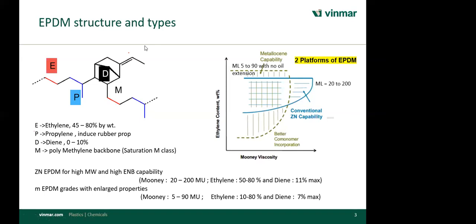Mostly in the world, EPDM is manufactured using solution polymerization technology. Only Versalis is making EPDM through slurry technology, and Arlanxeo has one plant for the slurry technology. Arlanxeo also uses their own innovation technology. The rest of the plants in the world are using either Ziegler-Natta or metallocene. Ziegler-Natta is the old technology, where the productivity of EPDM is low. Metallocene is the very first technology where you can get conversion up to 100% out of the reaction. In Ziegler-Natta, one can get a maximum of 80% conversion. So all the new plants are coming with metallocene capability.